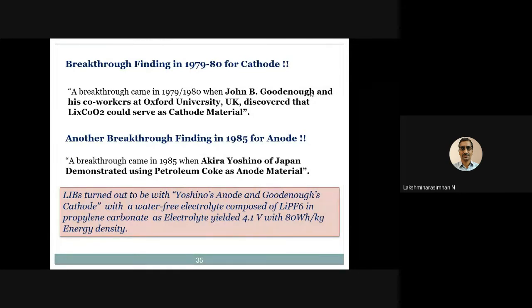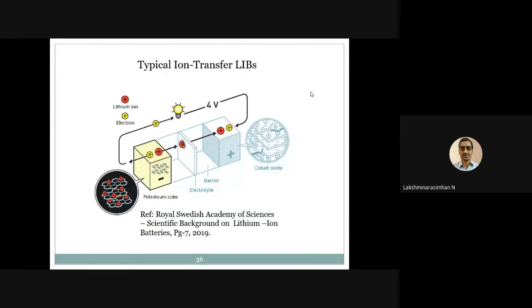People even spoke like this: if it is the anode, it's Yoshino's anode; if it is the cathode, it's Goodenough's cathode. With a water-free electrolyte composed of lithium hexafluorophosphate in propylene carbonate, they found the best voltage that they obtained, 4.1 volts with 80 watt hour per kilogram energy density. This was a major contribution, and that's how it went through. And again, if you solve one problem, you end up with another problem. There is some other problem actually waiting. That's what the whole session is going to be dedicated to.